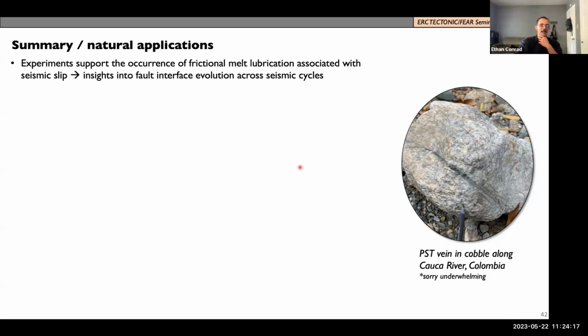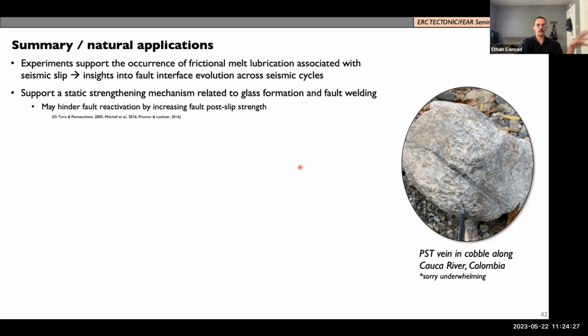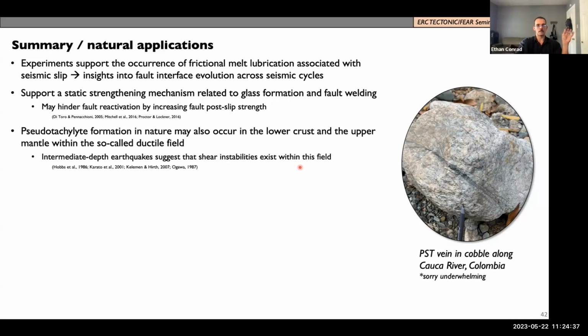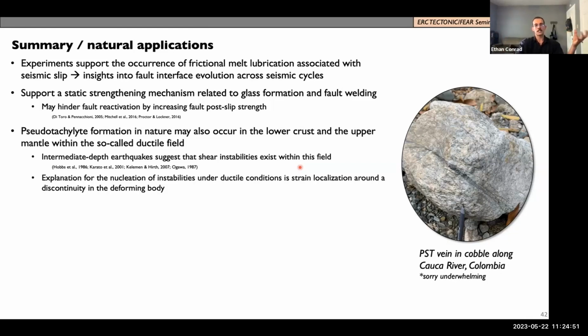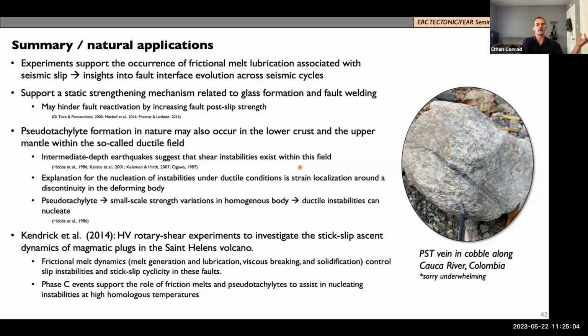So in summary, thinking about natural applications, these experiments support the occurrence of frictional melt lubrication associated with seismic slip, providing insight into the interface evolution. They support the strengthening mechanism as a result of the formation of glass and the welding of the interface. This may hinder reactivation of the fault. In nature, pseudotachylite formation may occur in the lower crust and upper mantle in this kind of ductile field. And so the question is, how do you generate shear instabilities within this field? But we have intermediate depth earthquakes. So one explanation is that the strain is localized around a discontinuity in the body, and pseudotachylite might provide a small scale strength variation in the body. So this is like thinking about how some of these things can be applied.